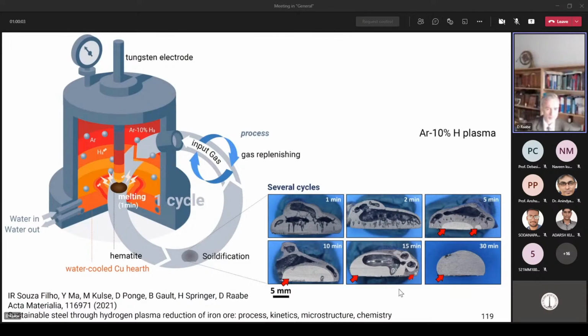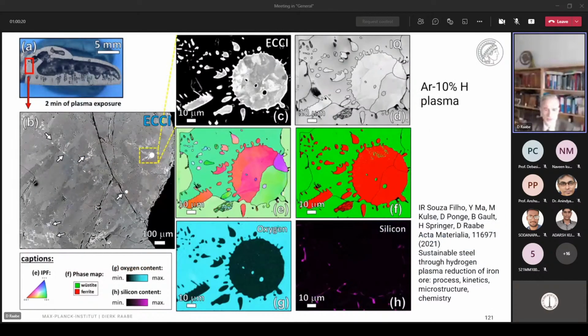Here you see the pictures of an interrupted process, after which we flooded the chamber again with the same gas mixture and went on. You see a sequence, up to 10, 15, 30 minutes. And already more or less after 15 minutes, probably after 20 to 30 minutes, you have pure iron in your hand. So with only 10% plasma content of hydrogen.